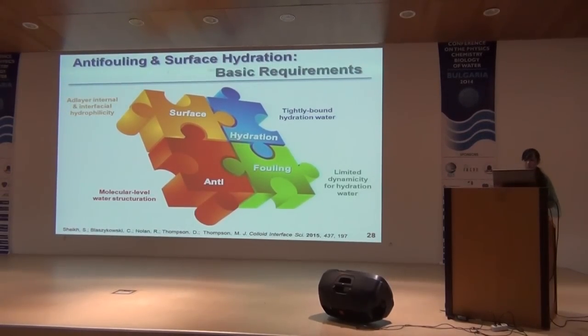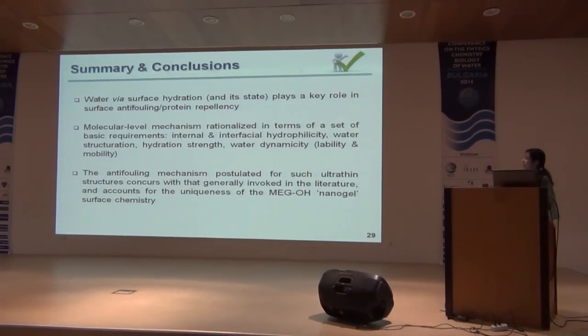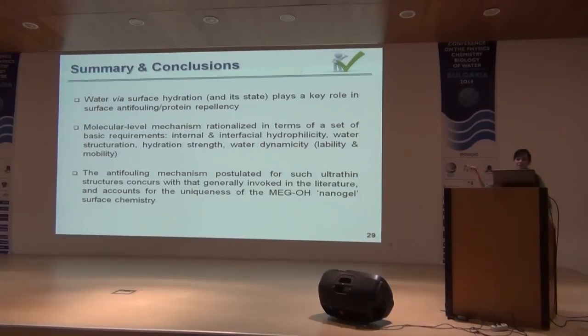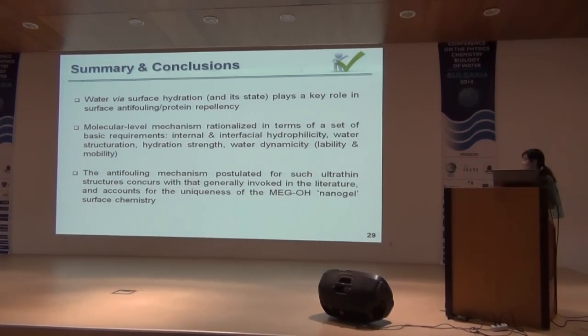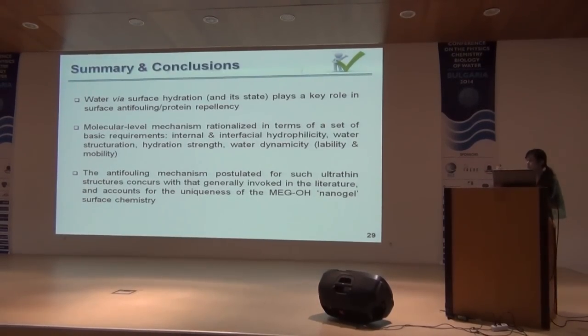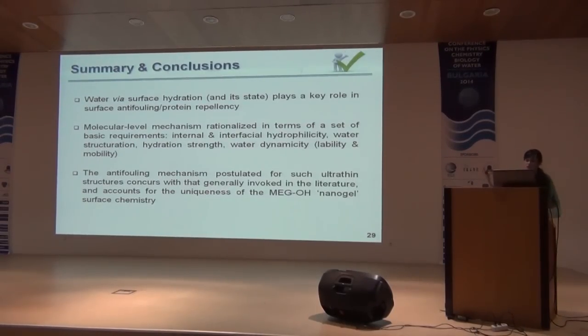In summary, water through surface hydration and its structural state plays a key role in surface antifouling and protein repellency. A molecular-level mechanism is rationalized in terms of four basic requirements: internal and interfacial hydrophilicity, water structuration, hydration strength, and water dynamicity — the lability and mobility of water. The antifouling mechanism postulated for these thin structures concurs with existing literature and accounts for the uniqueness of the MegOH surface chemistry. Our findings consolidate scattered ideas in the literature into one cohesive framework supported by experimental and computational evidence.